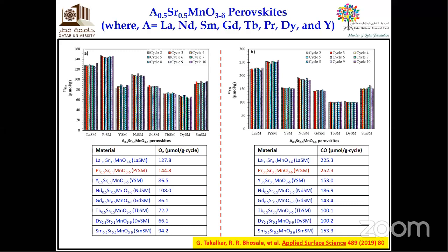Also, if you compare all these materials with previous studies which I have seen, you will notice that the perovskites are more beneficial than ceria and ferrite. That's why recently the solar thermochemical community is focusing on perovskite. But instead of focusing on any random perovskite, which is what others are doing, we decided to do this study, find the best possible perovskite, and then focus on only one perovskite which we can take to the next level. So we found that PrSrMnO3 is the best in this list.